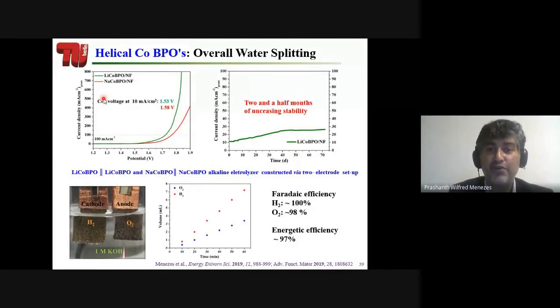So we also did overall water splitting. That means, as I already told you, we need to show that it is good enough for an electrolyzer. So we use the same material as anode as well as cathode, which is lithium cobalt or sodium cobalt borophosphate. This is the cathode, this is the anode, and we could test for almost 3 months. We tested already and this activity doesn't decrease. So this could be an ideal candidate to use commercially.